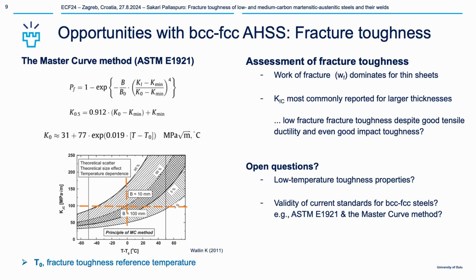Traditionally, this comes from pressure vessel steels, quench and tempered steels, and bainitic steels from the nuclear industry, as also shown in the previous presentation. There is the history, but it is applied to very many structural steels. So can we get something from that? Looking at the literature, many of these, for very thin sheets with similar microstructures, work with the work of fracture and then K1C. But looking a bit further, can this low fracture toughness really be true despite the good tensile ductility and maybe even good impact toughness properties?